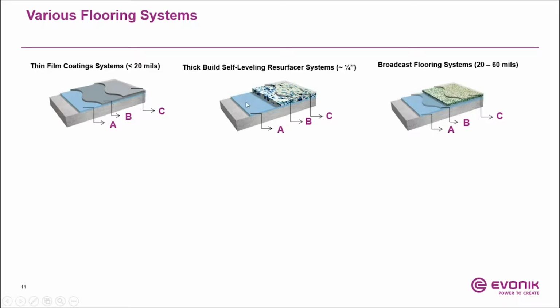Thick build self-leveling resurfacer type systems, you can really build very thick. A lot of times you use it where you have concrete that is not even and you need to smooth it out, or in industrial applications and things like that, where you need something more durable. What you're doing here is building the thickness through the mid coat. A lot of times you're adding some kind of cementitious or filled system as a mid coat. You can go up to 1/4 to 1/2 inch thick sometimes.